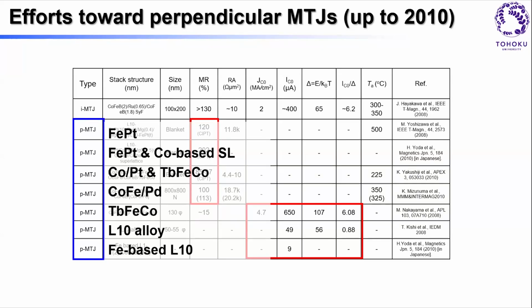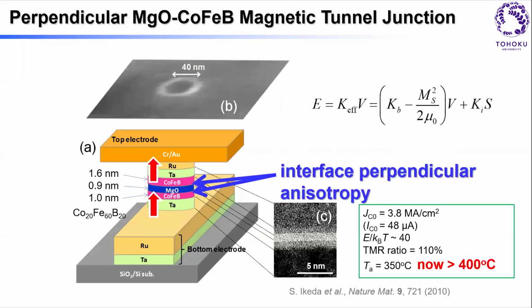And so there was a certain period of time that people struggled and struggled and struggled until 2010. We were happy seeing that this can actually be done by not adding new materials to the structure, but making the cobalt iron boron layer thin enough. The reason for this is that there's an interface perpendicular anisotropy between MgO and cobalt iron boron.